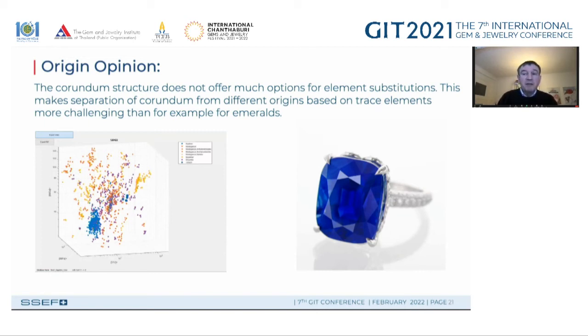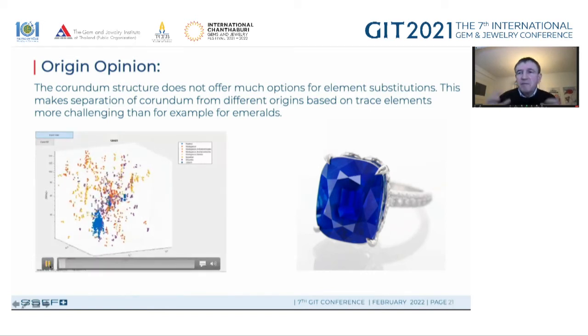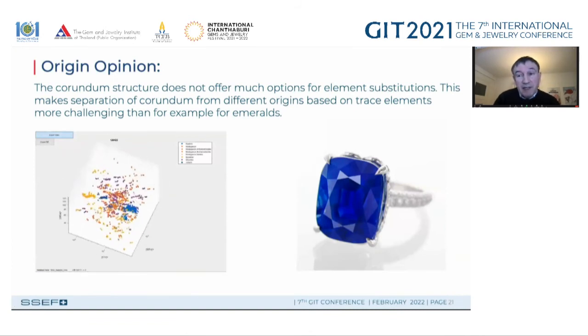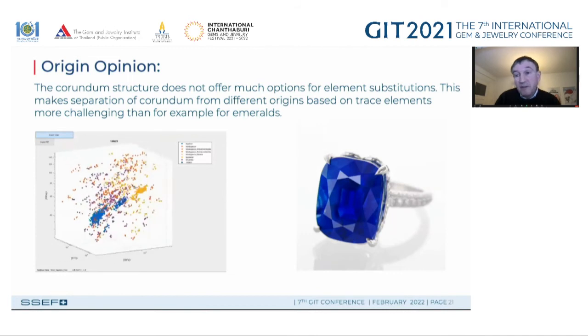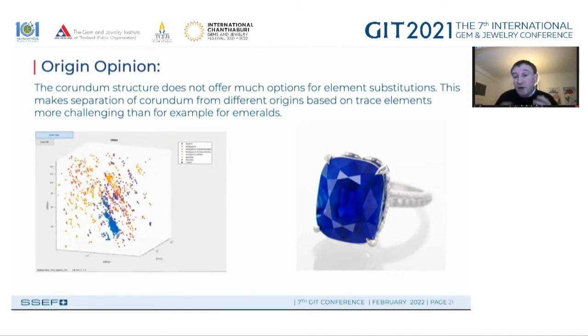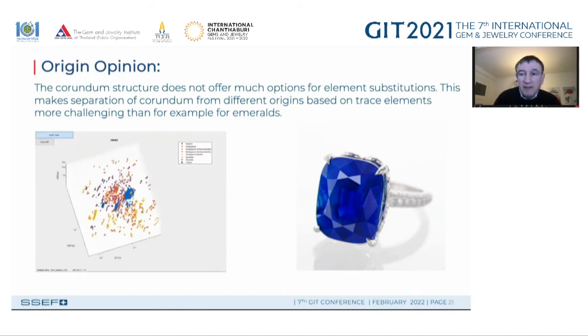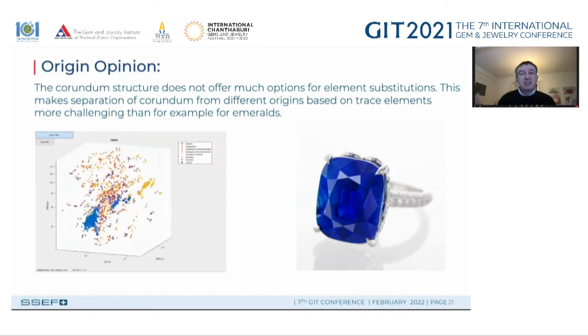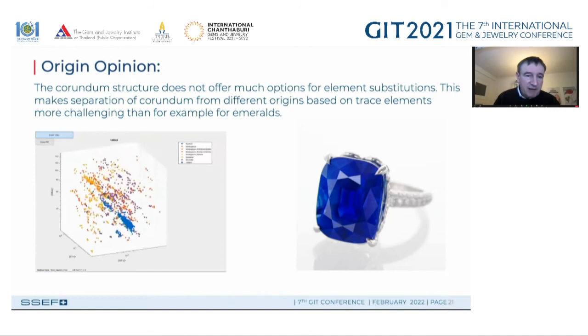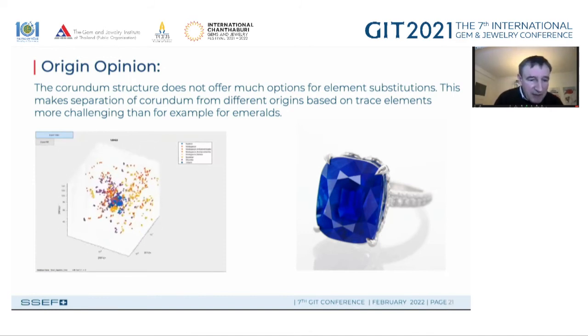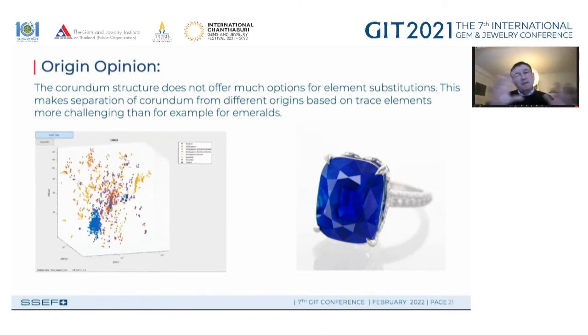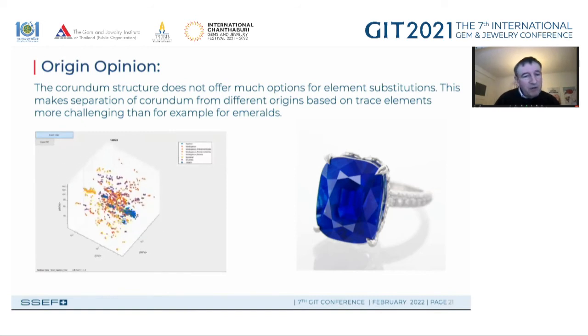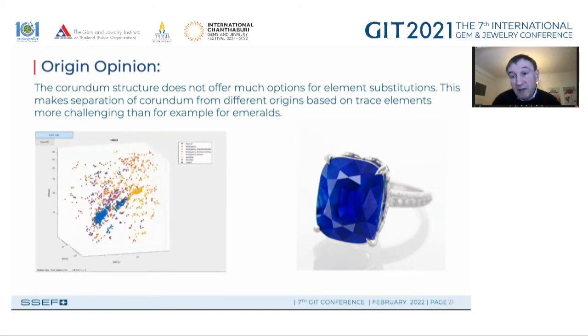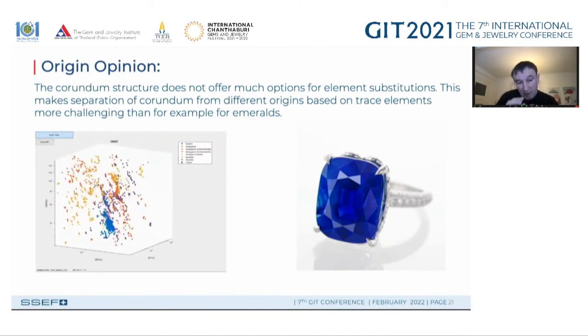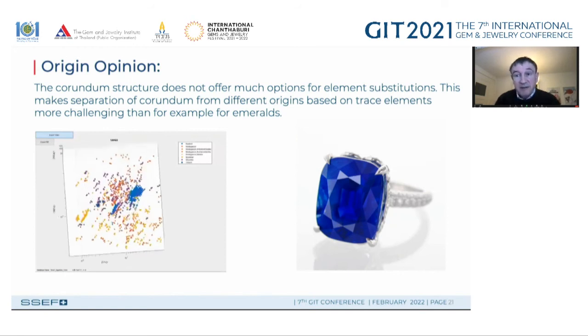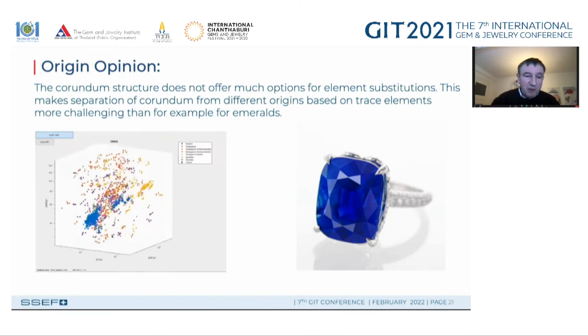But the problem with corundum is that these stones actually have a very, let's say, dense structure, and as such offer very little option for elemental substitutions. This makes identification, or let's say plotting, difficult, because we have not much options, and this is very different to emeralds, where you have a structure which can accommodate a lot of different elements inside. So what you see in this three-dimensional scatter plot with the elements iron, vanadium, and gallium is an overlapping situation. We can see a blue zone, and this is where we have sapphires from Kashmir, especially in this large cloud, the very fine quality sapphires from Kashmir. But again, it's quite difficult to work with this.